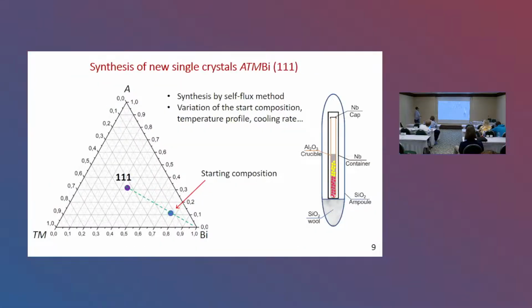In this slide we can see the experimental conditions for preparation of 111 single crystals. We used the flux method. This is the start composition for crystal growth. We put our precursors into an alumina crucible, seal this crucible in a niobium container, and then seal this container in a silica ampoule.